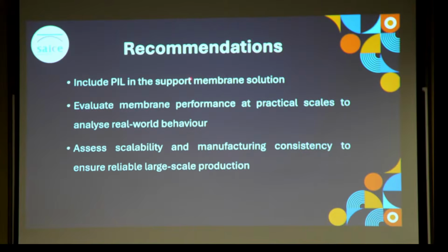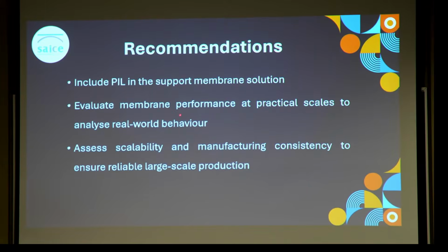It is recommended that future investigations incorporate the PIL into the membrane support solution rather than adding it after the support membranes have already formed, to better improve integration. It is also recommended that larger membranes be fabricated and tested to better align the results with what is expected in commercial desalination plants. Thank you.